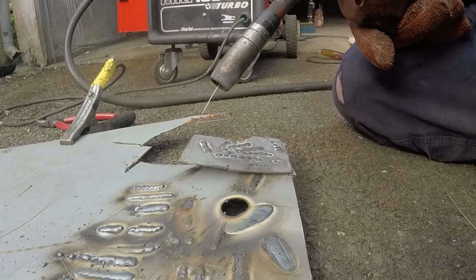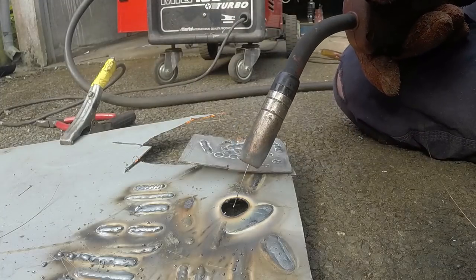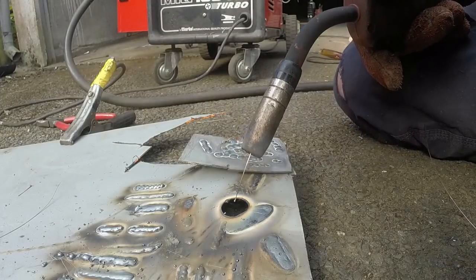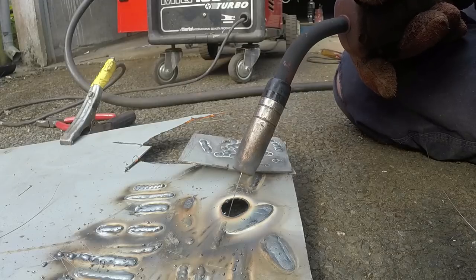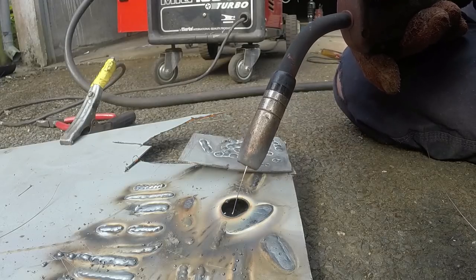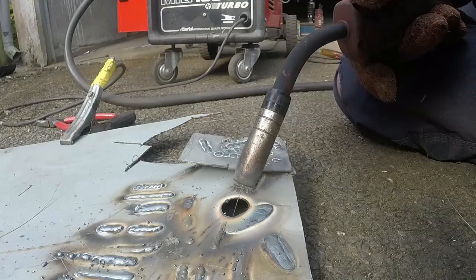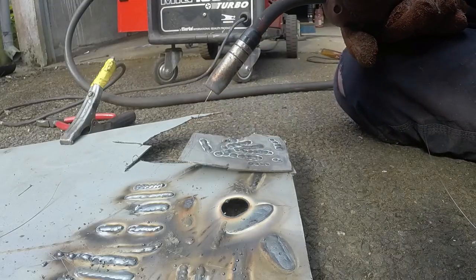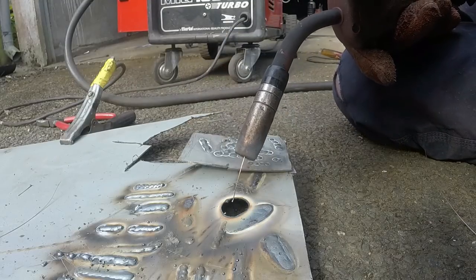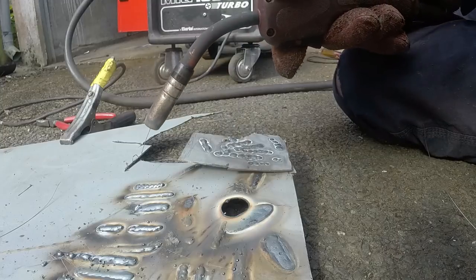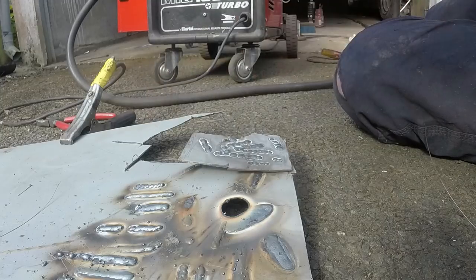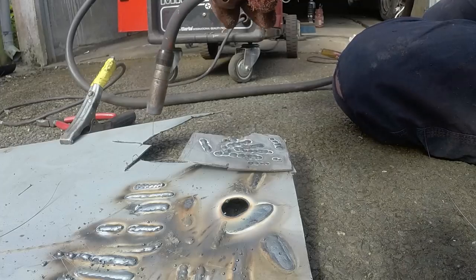That's an extreme example, but basically the weld pool gets so big that gravity alone and the force of the weld just blows a big hole. You will get that on thin metal at lower weld settings, particularly when you're at the edges of something. So if I go back to a more sensible setting and try and weld that up.